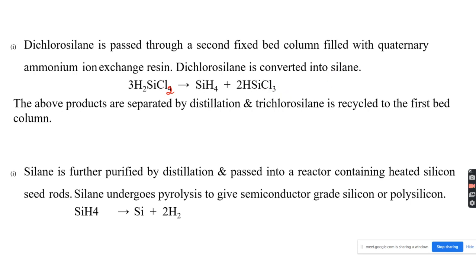We will get dichlorosilane and the tetrachlorosilane. Trichlorosilane is recycled, and the dichlorosilane is converted into silane. This way we are able to get silane, SiH4. The above products are separated by distillation and trichlorosilane is recycled to the first bed. Then further the silane is converted into pure silicon: it is purified by distillation and passed into a reactor containing a heated silicon seed rod. So silane undergoes pyrolysis, very high heating, to give semiconductor grade silicon or polysilicon.